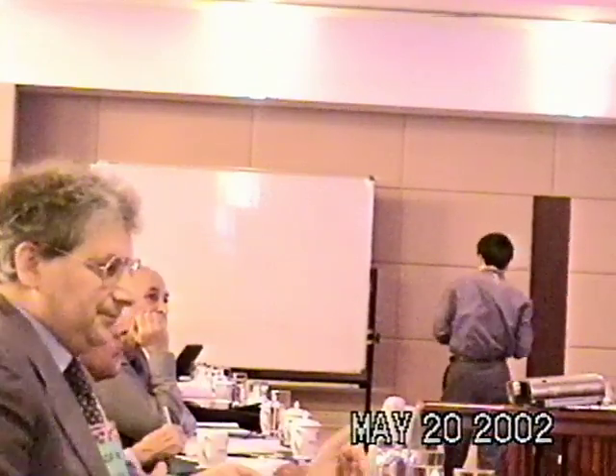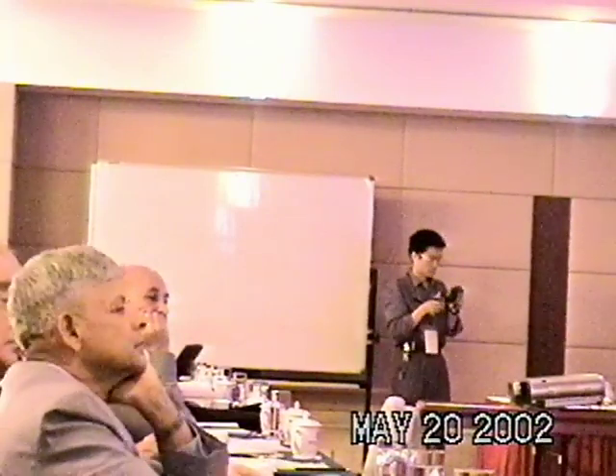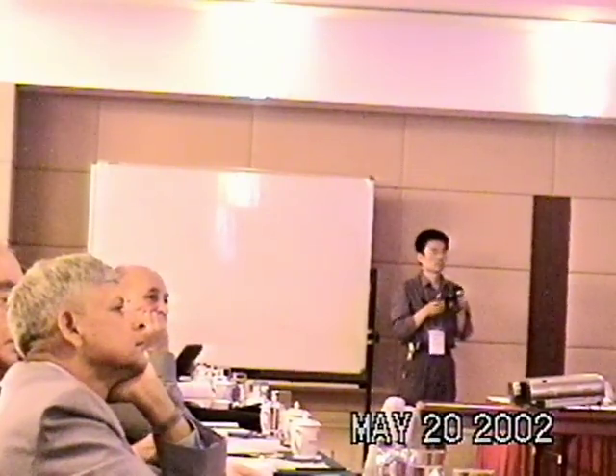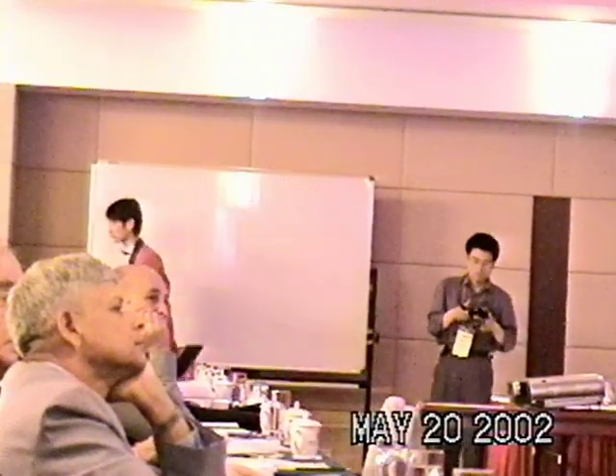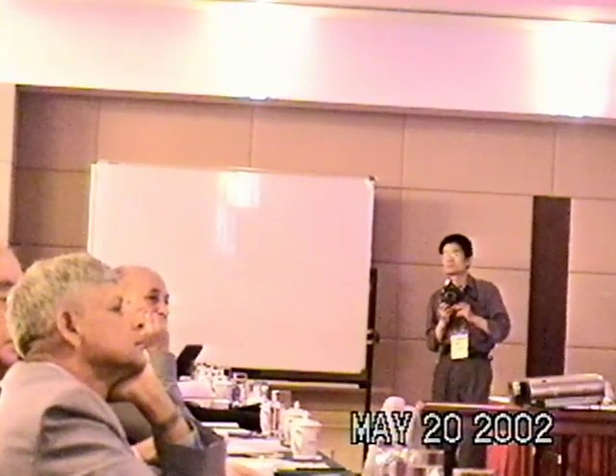We produced a table that will be shown in the poster this afternoon, in which we report the maximum height for several load and deload cycles. And you can see that the deload maximum is always higher than the load maximum. But the dynamics of the sample tends to shrink from one load to another. I think that is because you cannot be sure that you deload completely your samples after the experiment, because we do not invert the electrolytic current. So if you don't evaluate correctly the R0 values, you can have a big error on the evaluation of the peak.